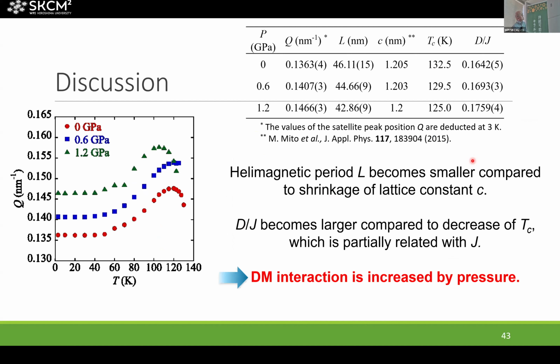Then from these results, we can extract the period of the chiral magnetic state, and also the transition temperature and the ratio of the Dzyaloshinskii-Moriya interaction and the exchange interaction. The helimagnetic period becomes smaller with increasing pressure, but this ratio is not similar to the shrinkage of the C-axis. The C-axis is the chiral axis. When the C-axis shrinks, the period shrinks, but the relation is different.